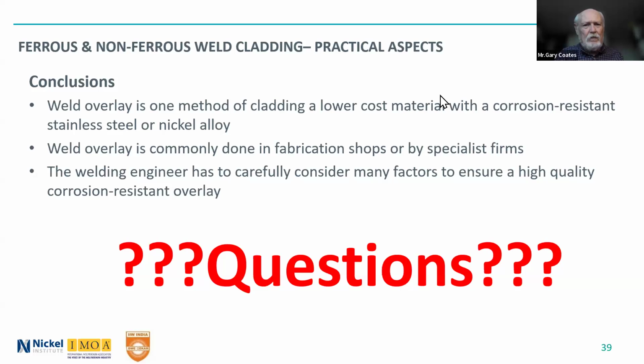So the first one is in sour service. Do we need post-weld heat treatment for cladded overlay material weld joint? In the particular case, it's 28 millimeter X65 pipeline steel with a 5 millimeter 625 overlay. What is the post-weld heat treatment temperature? I would have to look that up, but generally I would say yes. When you get into those kind of thicknesses, as far as I know, with most materials, you really do want to do the post-weld heat treatment, and you usually want to do it after the first layer.